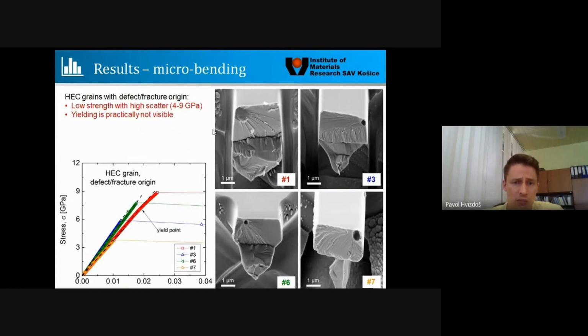In the case of defected cantilevers, we see everywhere that the fractures originated from the defects, not exactly from the pores, but most probably connected with cracks formed around the pores, and those cracks propagated and resulted in the final failure of those cantilevers. And of course, depending on the location and the size of those pores and initial cracks, the strength varies between 4 and 9 GPa, and because they are present and fail immediately when reaching the specific value of fracture strength, there was no yielding observed.